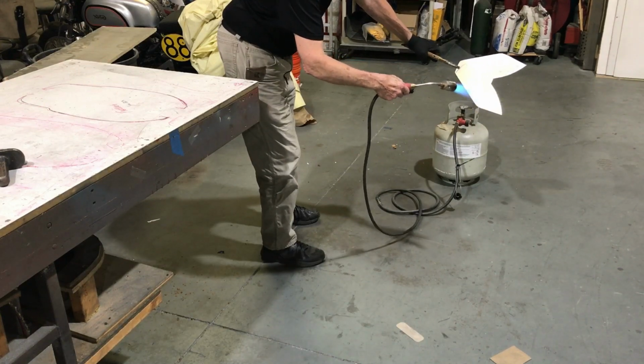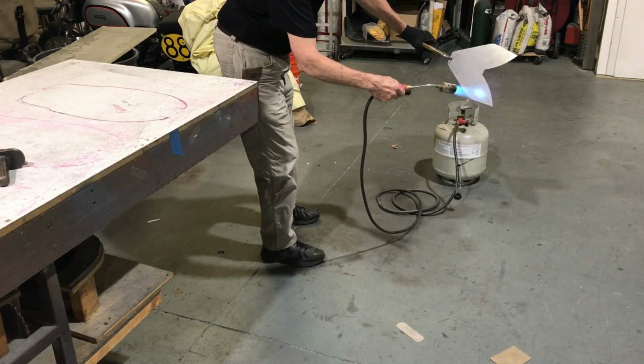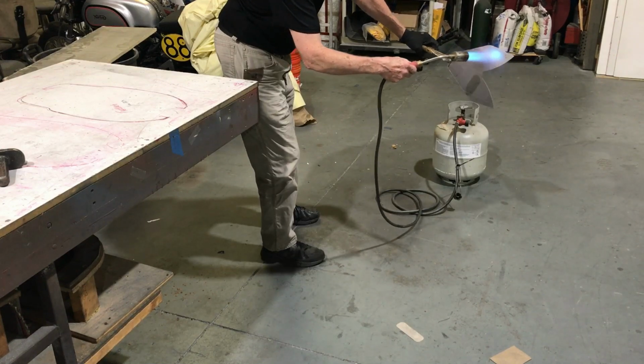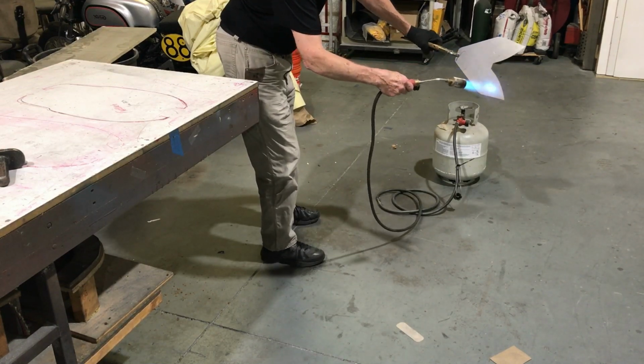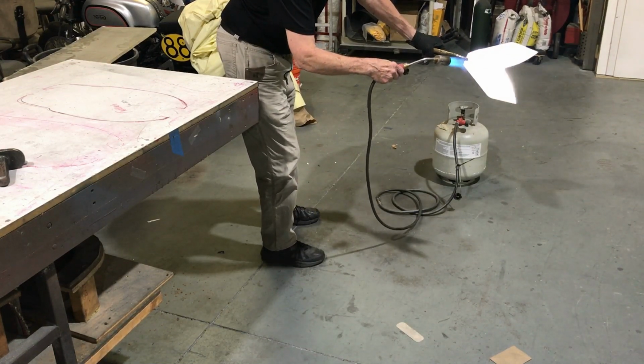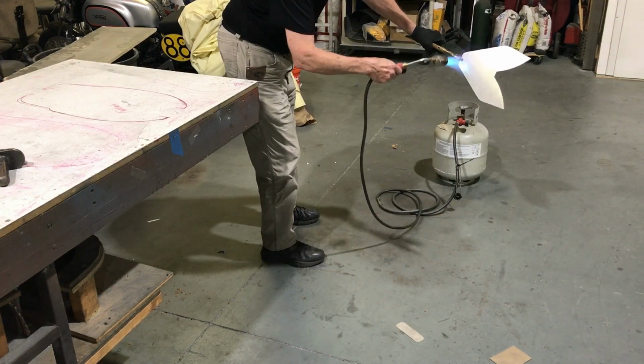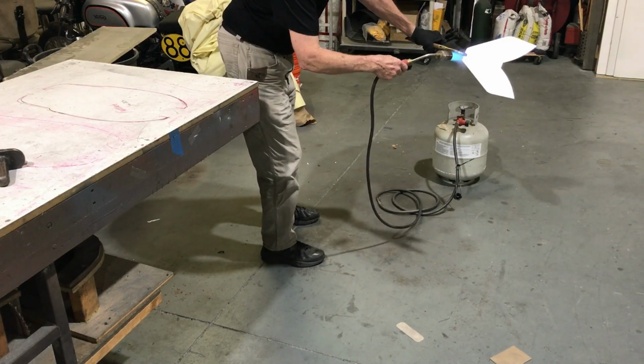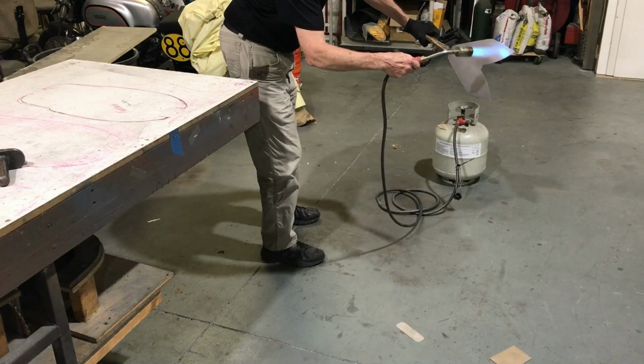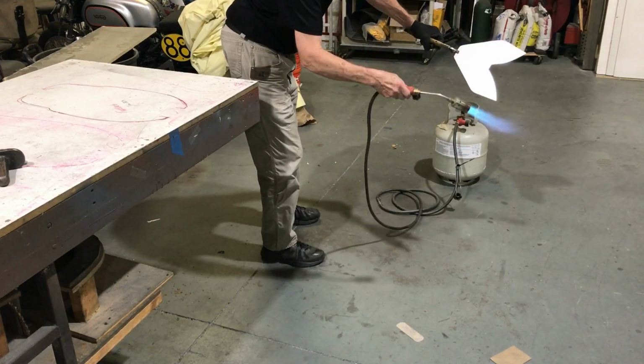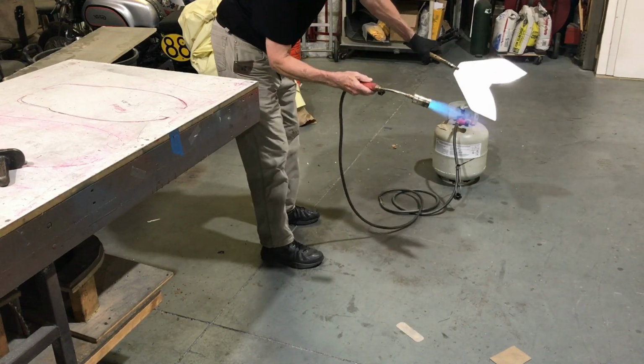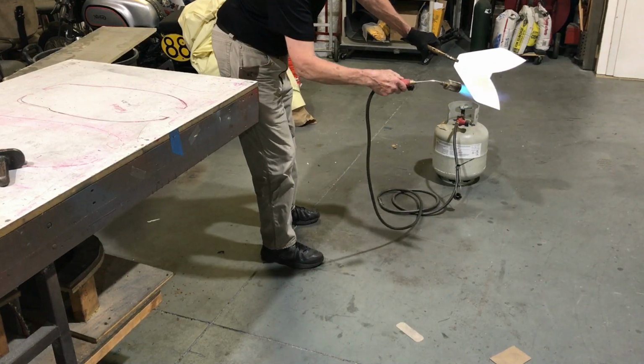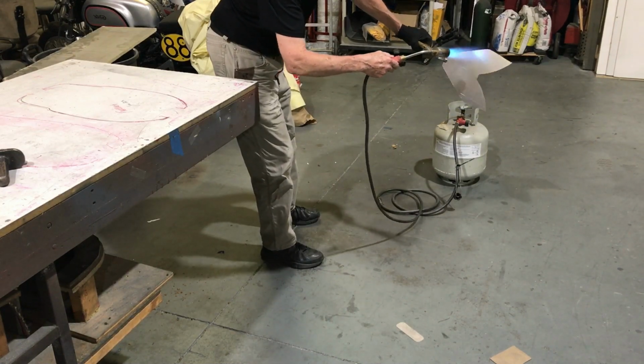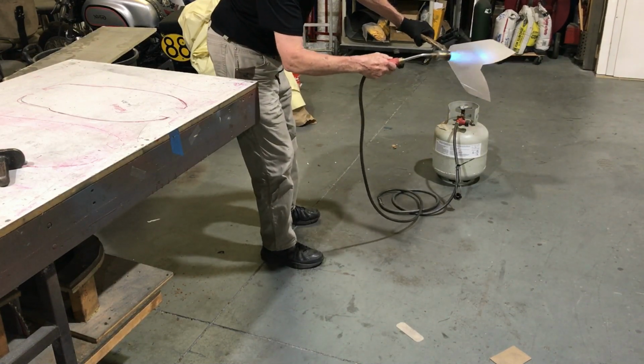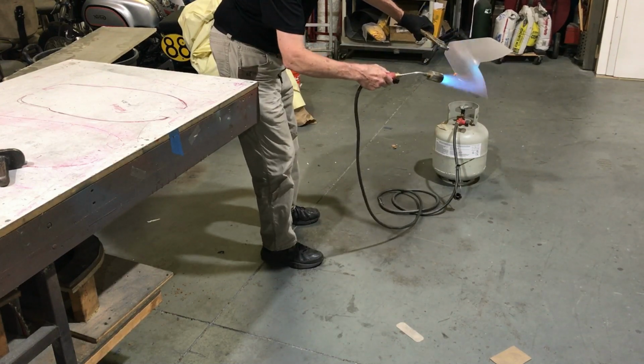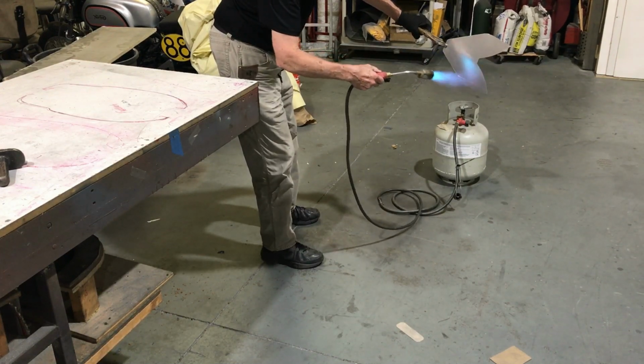Now with the soot method, the soot acts like insulation. If you have it on too thick in some spots, you're going to have some harder spots on your aluminum. This one, you can see the wires are soaking up some of that heat on there. I'm going to hit that pretty hard. Alright. Black is gone. Now, next little thing we got going on here is the aluminum gets real shiny just before it burns. Just stay on the outside of it. Don't go to the inside. That'll burn right inside there.